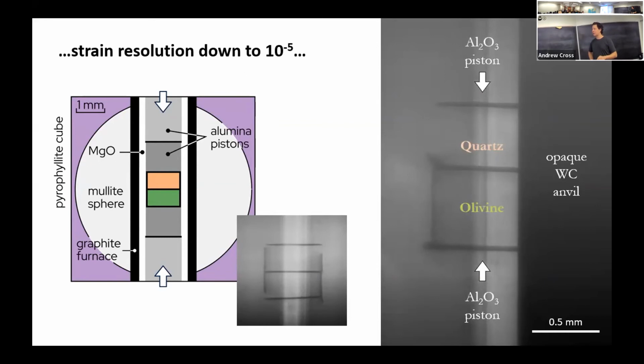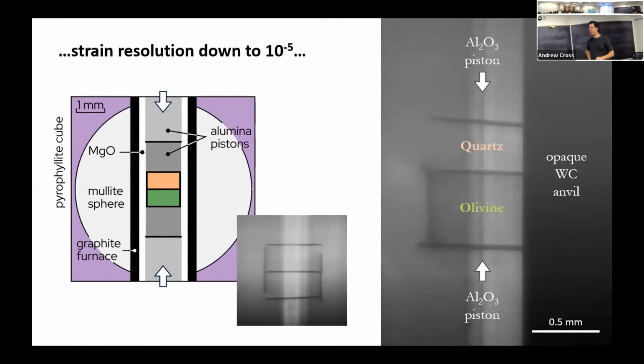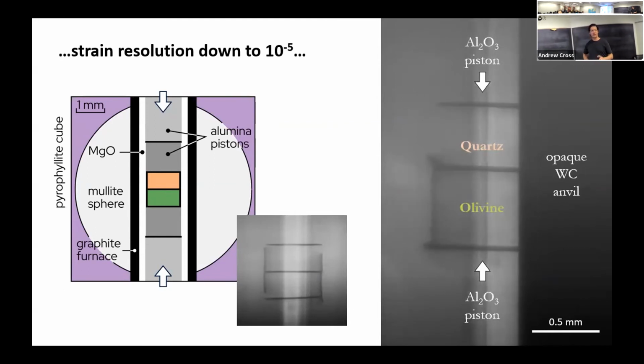This is just a sample of quartz being squeezed uniaxially, and we've got our olivine sample down below, which ideally we want to use as an elastic standard for getting out stresses. We use this effectively as a stress sensor because the elastic properties for olivine are pretty well constrained as a function of pressure and temperature. And so we'll take each one of these radiograph images and do a digital image cross-correlation. That gets us down to about a microstrain resolution, so we can resolve really small sub-pixel changes in sample length and strain.